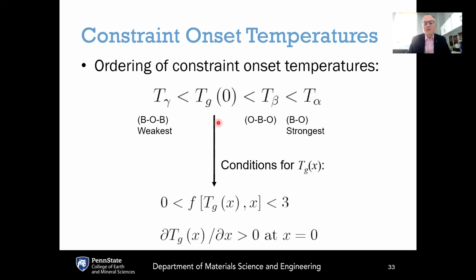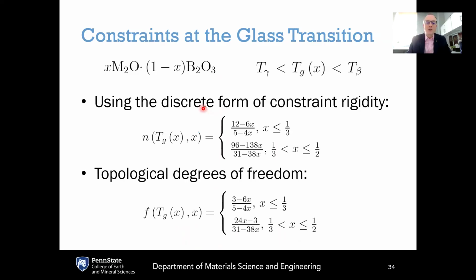And this is mathematically determined based on two conditions. The number of degrees of freedom at the glass transition temperature must be less than 3 in order to induce a glass transition, but still must be greater than 0 if the system is still experiencing flow. So we know it must be between 0 and 3. And also we know that the derivative of the glass transition temperature with respect to the modifier concentration must be positive at x equals 0 because of the formation of tetrahedral units. And therefore, with these two conditions, we've deduced where the Tg must be.